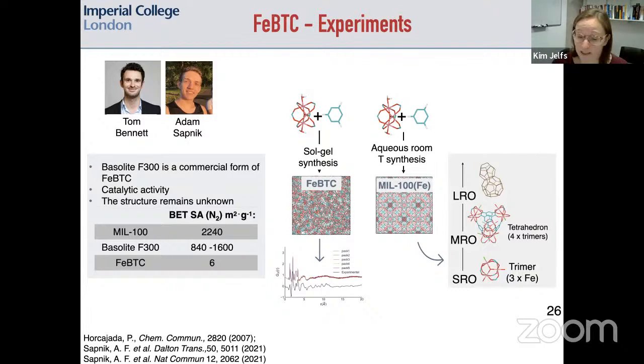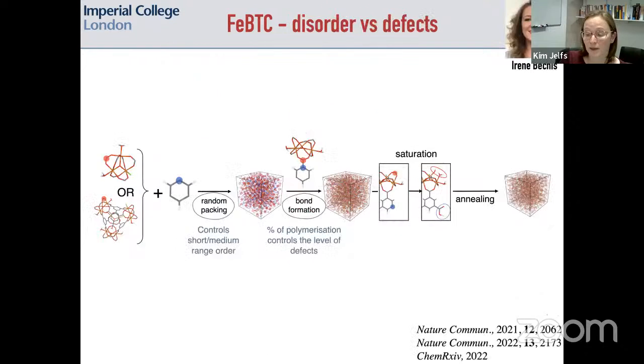But actually, we were really surprised. We used an approach that I'll explain in a moment to try and predict amorphous structures. And we were really surprised, when we compared to a lot of the scattering data, how good a job we were doing at reproducing those. So I think the method by which we build them is relatively simplistic, so I don't think the model's perfect, but actually it's surprising the agreement we have. And so I think some of the insight that we get is pretty useful. So this was work in particular done with Irene, who's just finishing her PhD in my group now.